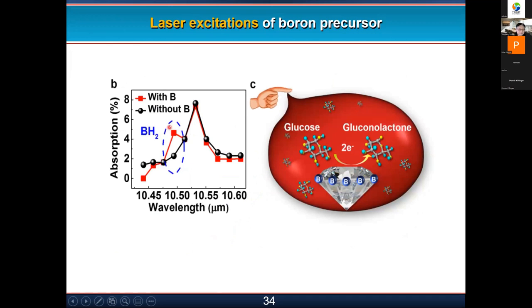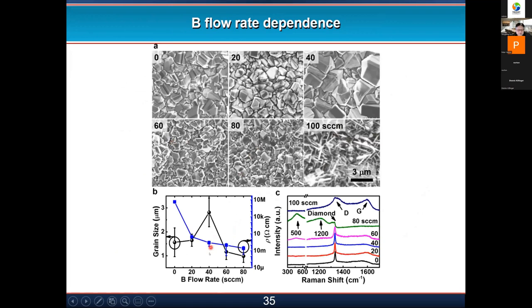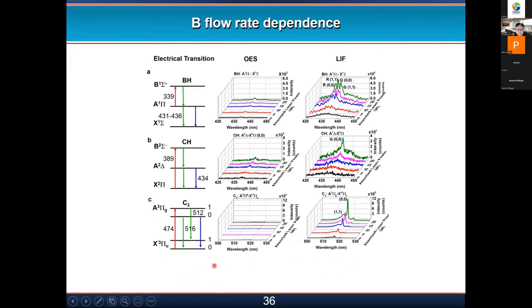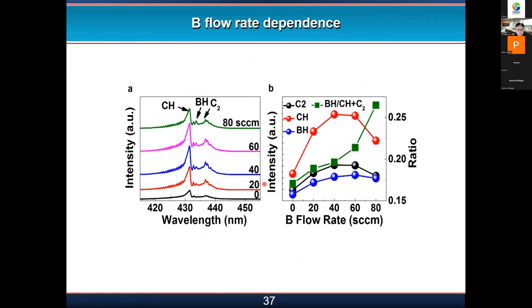There's one resonant frequency corresponding to BH2 here, and we can see there is a peak we can match to excite BH2. Similarly, when we tune the boron rate, there's an optimum boron concentration in the flame, and when you have less or more boron, the crystallinity will be worse. Then we studied the chemical reactions using optical emission spectroscopy and laser-induced fluorescence to understand what kinds of species are being produced by this combustion flame, and how the boron rate affects the chemical species in the flame.